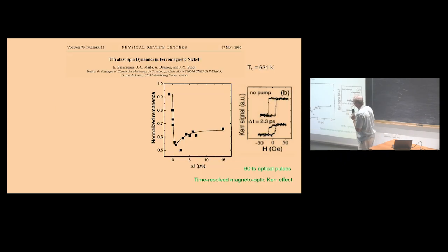A frequently cited paper is this one, already almost 30 years old, where this group used femtosecond optical pulses in the visible range to illuminate a nickel ferromagnet. They observed fast demagnetization of this system within 1 picosecond. This is a really very fast effect. They measured the magnetization using the magneto-optic Kerr effect, which I will speak about on the next slide. But why is this happening?